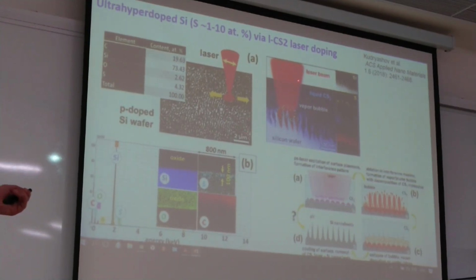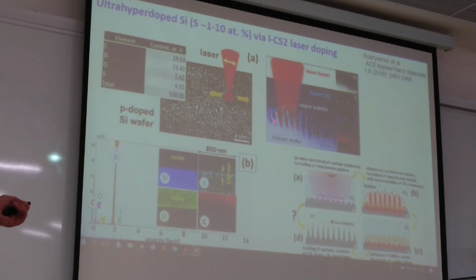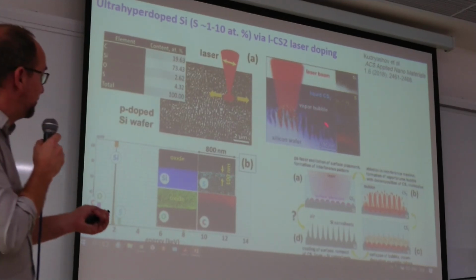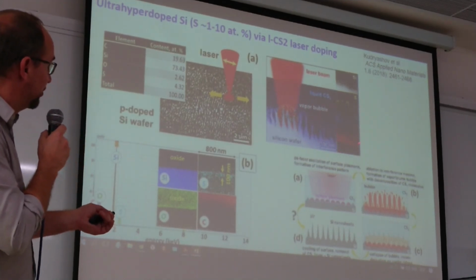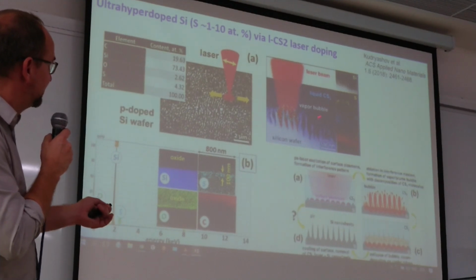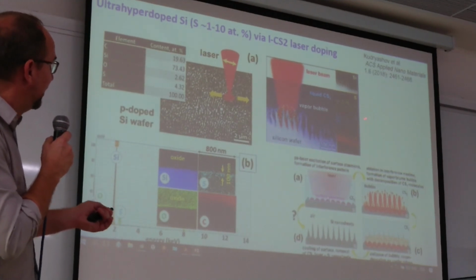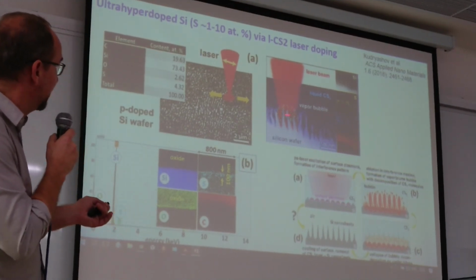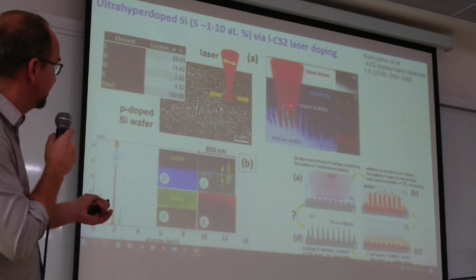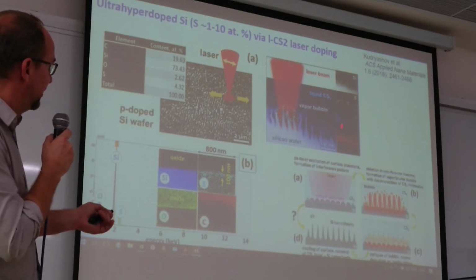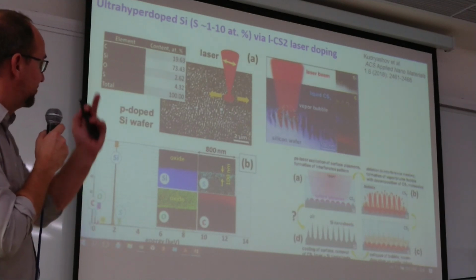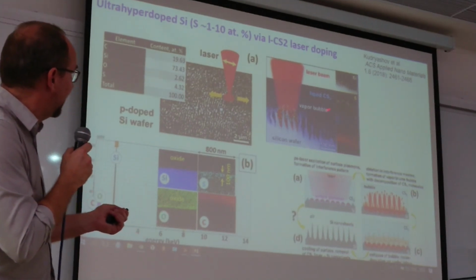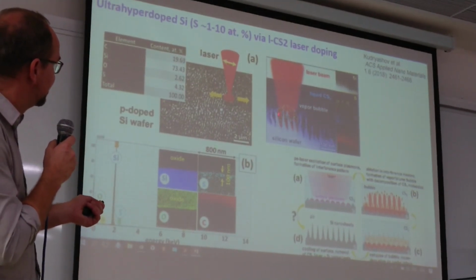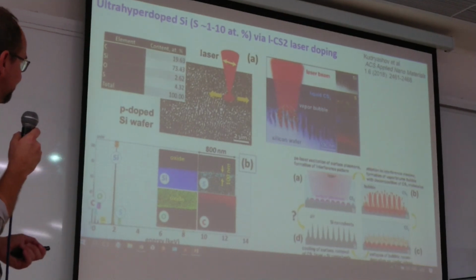So the technology works like this: when we are scanning the surface, we are producing these periodic structures, and in these periodic structures, carbon occurs on the top as a carbon layer. Oxygen also oxidizes these silicon ripples, silicon spikes, but sulfur enters inside these spikes.